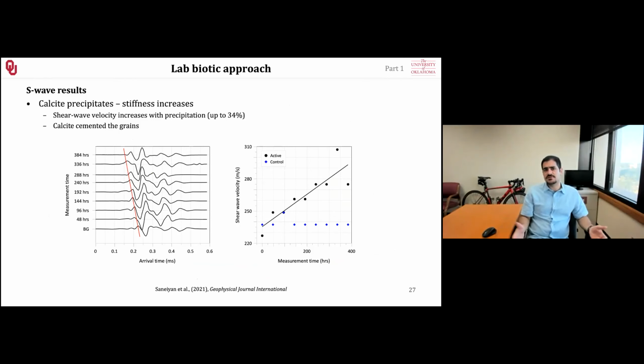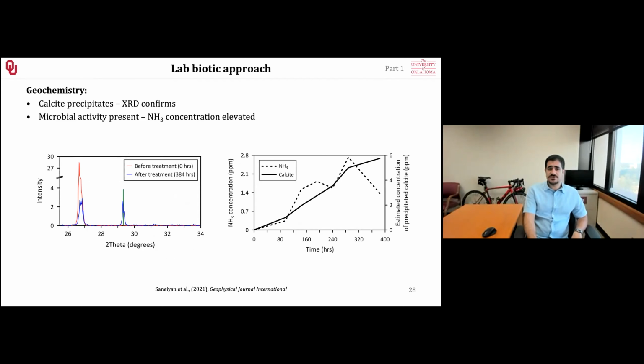Again, we are just using calcite inside our column, and the bender elements are at the same location and so on. But clearly it shows us the calcite cemented the grains together. So microbial induced calcite precipitation works as a soil stabilization method. Geochemistry also proved it. We were unable this time to use SEM microscopy, so we did XRD instead. So we took our samples and put them under XRD, and were able to see that the untreated soil did not have any evidence of calcite in it compared to the treated soil.